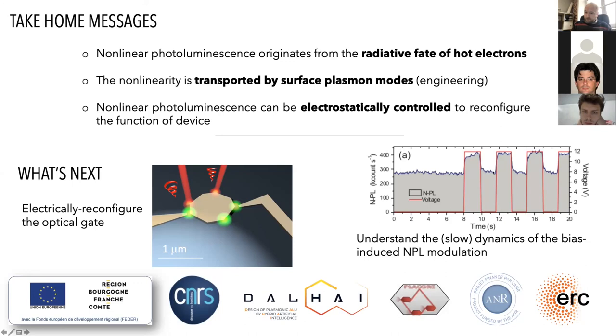So you see this slow dynamics here. I don't know if you can see my cursor here. You have a slow dynamic which is associated to this, and this is linked to modification of the gap. So it's a stress-induced modification of the gap when you apply the bias.